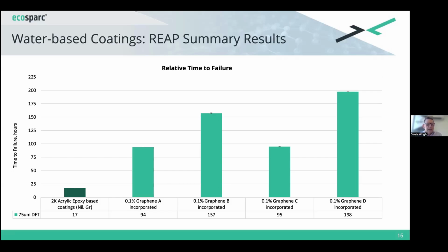That's the other piece. Quickly touch on that. Depending on the coating and depending on the solids of the coating and the brittleness of the initial coating, changes your grade of graphene and the percentage you want to put in it. We start off as, if you've got something that's about 70%-ish, you go with about 0.1. So that's our starting point. If you put too much ecosparc in or graphene-based additive in, you will damage the performance of the coating. The performance actually goes down. If you don't put enough in, then there's space there for improvement. So there's a sweet spot around the 0.1.